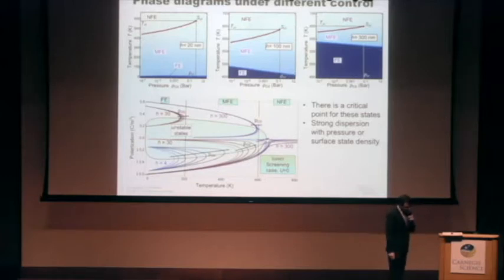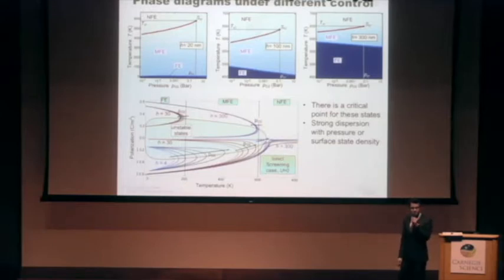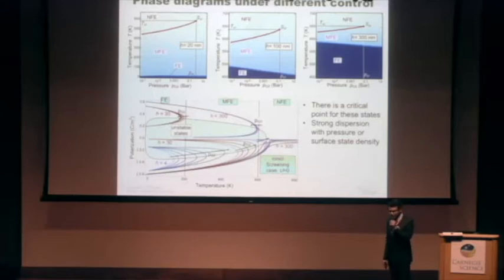One of the interesting finds from piezoresponse force microscopy studies in maybe the last decade or so is that it seems that you can possibly, I should say, because PFM has a lot of artifacts, obtain a range of polarizations in ultra thin films. And so the question is, what is the origin of these types of effects? One of the possible origins is explained by this particular theory.